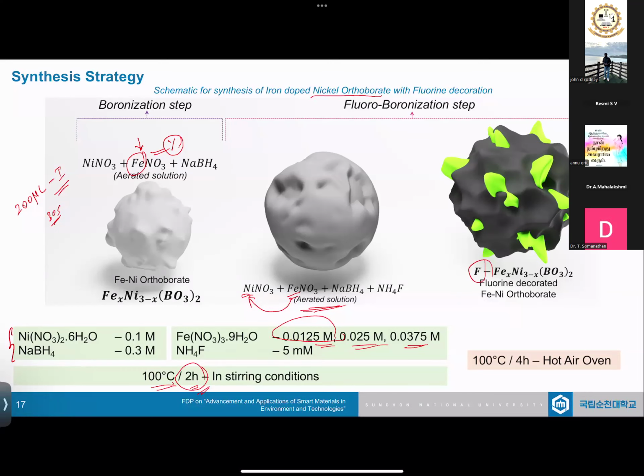In this same process, 5 millimole of fluorine source was added to the system. And what happened is, we planned on bringing the fluorine. Because of the temperature being present, we thought that this fluorine will etch the surface, exposing more sites, more planes, so that it enhances the activity, because we know disorderedness and defects give a good output with respect to OER and HER. So this was the basic plan that we had. So with that, we went on further.